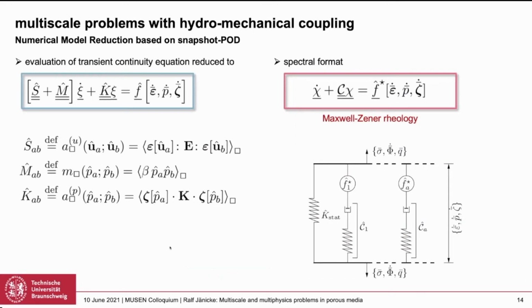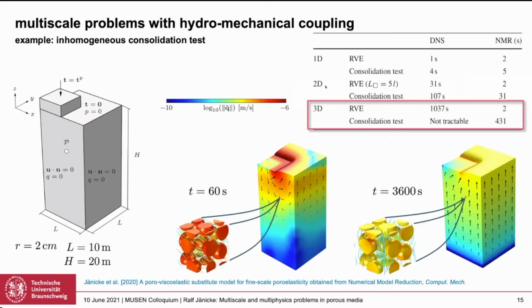The entire transient problem is reduced to solving an evolution equation for these parameters psi, where all these system matrices can be pre-computed. These are sensitivities on the pressure modes. It can be further simplified in the spectral format. Then it looks like this, where C is a diagonal matrix, so it's really a decoupled ODE system. Finally, this has the same structure as the Maxwell rheology in viscoelasticity. Therefore, we also call this resulting large-scale model poro-viscoelastic, even though the mechanisms are not comparable to classical viscoelasticity. So solving the two-scale problem means online solving the macro-scale equations, and instead of solving the RVE problem, we only solve on top of the macro-scale equations a local ODE system. That's why it's way cheaper.